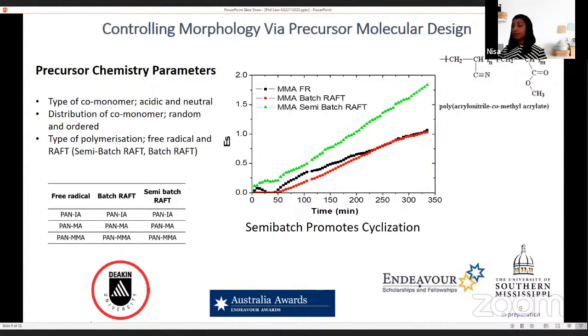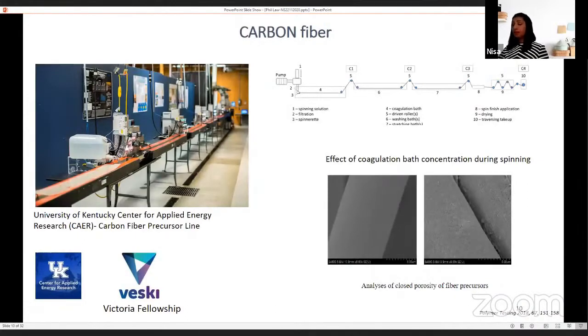Once we completed the synthesis, we conducted stabilization studies on these polymers. This is the most critical and time-consuming step in carbon fiber manufacturing. During this stage, the fibers attain the stability to withstand high temperature carbonization. We found that the polymers synthesized by controlled polymerization promote cyclization reactions, and thereby the stabilization process. Once we synthesize the polymer, converting these polymers into white fiber is the critical part in carbon fiber production. So to learn more about the wet spinning process and to get training on the pilot scale fiber spinning facility, I visited the University of Kentucky.